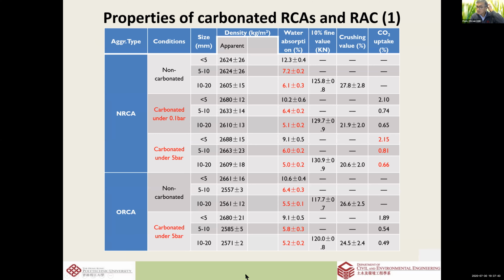And this comes back to our recycled aggregate. For example, the new one is 6 months old. Then without carbonation, the water absorption is very high compared to natural aggregate, where the water absorption is about 2%. For the new recycled aggregate it is about 7%. After carbonation, the water absorption will reduce by a certain percentage, about 10%.